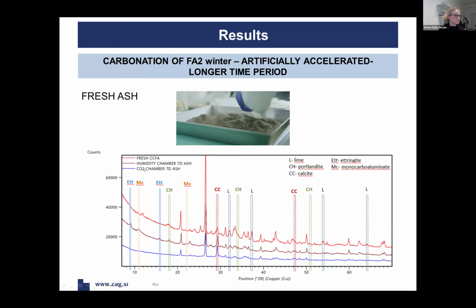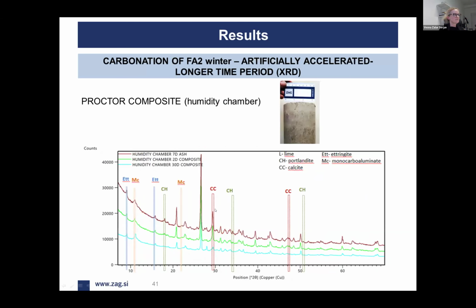In contrast, in a CO₂ chamber, practically nothing much is happening because of the lack of the water content, which was shown earlier in the beginning of the presentation, and this is another confirmation also at the longer time period, so after 7 days.